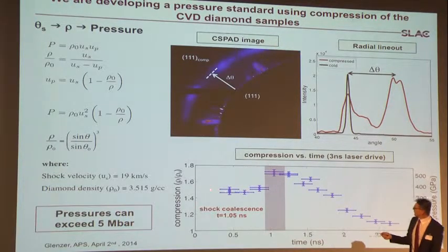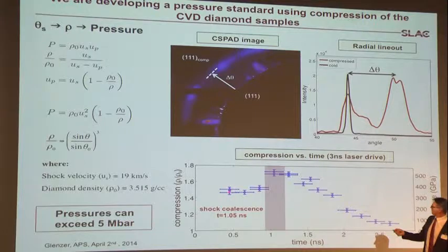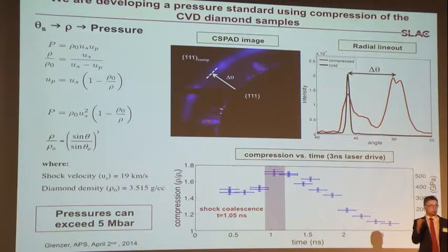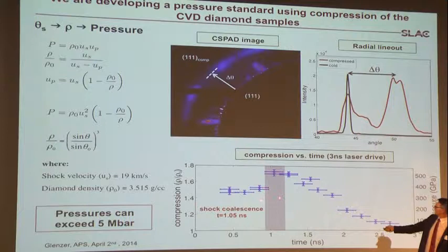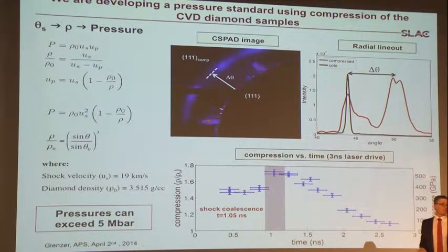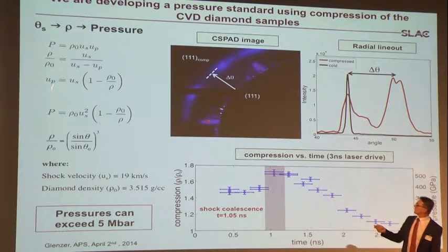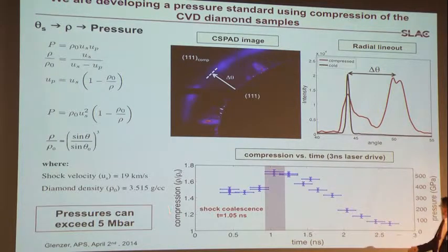And what is happening is, first of all, as a function of time, you see how the data show a certain compression. Those are just the shock waves as they're propagating in the diamond. And at about 1 nanosecond, the shock waves are meeting, they're coalescing. And then the density jumps up, and you can actually see this in the 2θ. The 2θ jumps up further, and then the lattice is relaxing. So from this measurement, we actually know the shock velocity. We know that the two shocks have met after 1 nanosecond. So now we have the shock velocity, and we have the compression. So now we can look at the Hugoniot relations, and that's how we go from compression to pressure, and you see those data are roughly between 4 and 5 megabar.